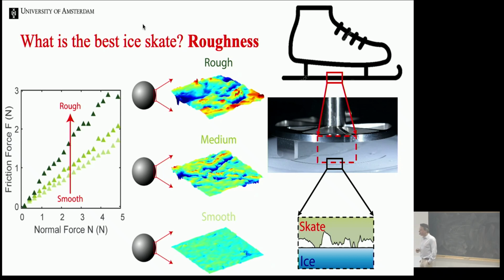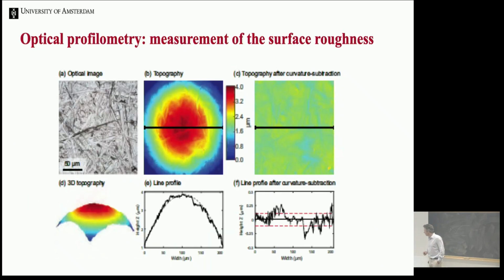However, that means that I need to measure or infer somehow the pressure, and that's not an easy thing because these roughnesses are terribly complicated. But I can measure them, and so what we typically do is we have the spheres, we can roughen them, we shake them in a little container with a bit of sandpaper, for instance, and then we have this profilometer that allows us to get a roughness map. We subtract the curvature of the sphere, and then what we end up with is a measure of the roughness of my surface, or even a complete map of the roughness of my surface.